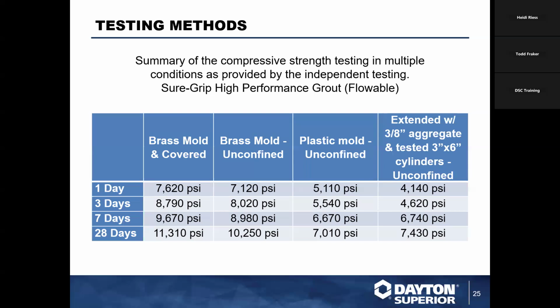You'll notice the difference in strengths. It's significant. The one we recommend is per ASTM right down the line. That's a brass mold and covered. You can use the brass mold uncovered and you'll lose 500 PSI. You can use the plastic molds, which are the little plexiglass guys that are not covered. And sometimes they'll put a little like ice cube tray in there. They're plastic, and you drop it down by another 2100.